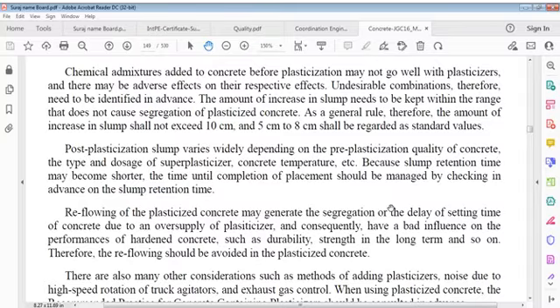Chemical admixtures added to concrete before plasticization may not go well with plasticizers, and there may be adverse effects on their respective effects. Undesirable combinations, therefore, need to be identified in advance. Amount of increase in slump needs to be kept within a range that doesn't cause segregation of plasticized concrete. As a general rule, therefore, amount of increase in slump shall not exceed 10 cm, and 5 cm to 8 cm shall be regarded as standard value.